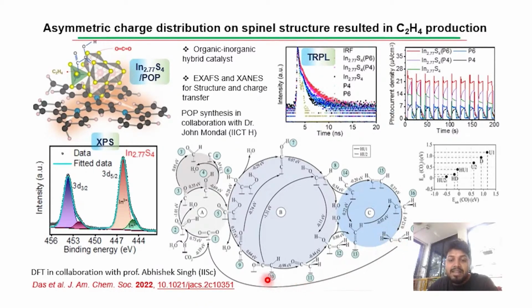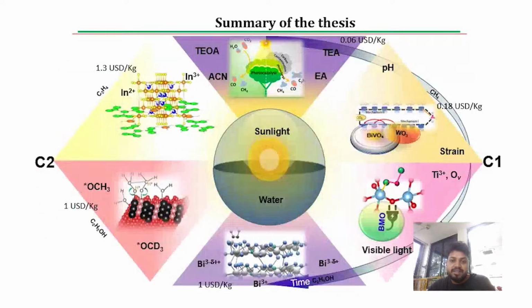If we could have seen this kind of oxygen bound intermediate as a stable intermediate, we might have got some oxygenated product like acetic acid or ethanol. However, as this was destabilized, which we proved from the DFT calculation in collaboration with Professor Abhishek Singh from IISc, we showed that the ethylene formation is much more facile in this kind of catalyst surface.